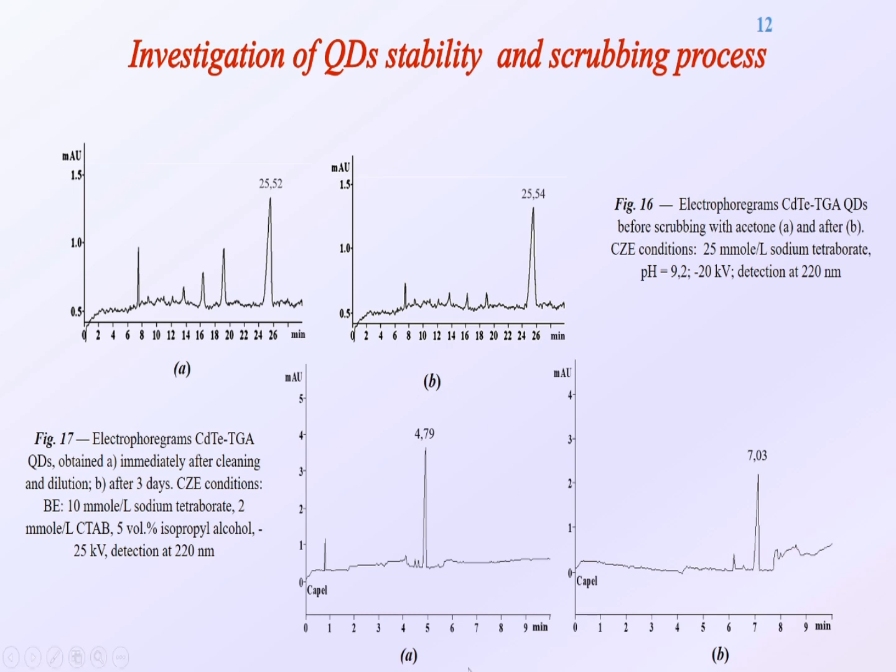And this slide shows electrophoregrams obtained immediately after the synthesis of quantum dots and after 3 days when stored in an aqueous solution. The observed shift in the migration time of quantum dots on electrophoregrams may indicate the process of aggregation.